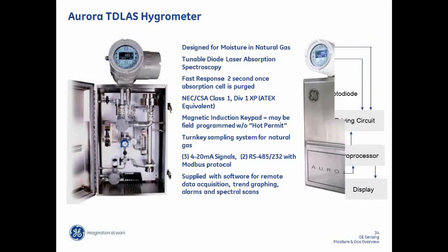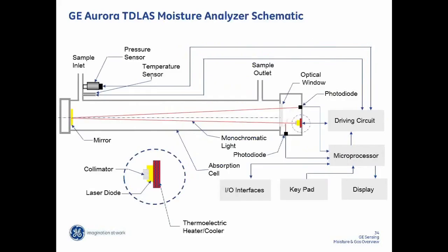The principle behind this is that we have a stainless steel tube, essentially, and inside that stainless steel, it's actually polished stainless steel, so it's a very smooth surface. And hermetically sealed away from that is a laser emitting unit, a diode laser, and there's an optical window made out of quartz. So the laser beam is shot down to a mirror. The mirror is gold-plated, and then on top of the gold is a silica coating, which is essentially like glass. And that mirror is only used to double the path length.